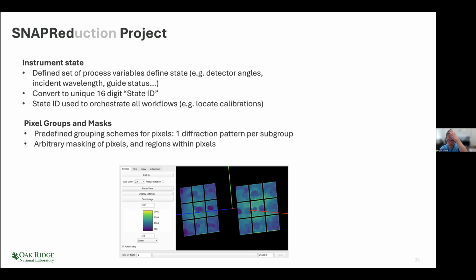And then finally, it also supports arbitrary masking of pixels and regions within pixels. And this shows a typical mask which has been applied to remove those diamond spots. And just to underscore, the binning and the histogram minimum and maximum limits are all recalculated on the fly to respect any masking which is done to remove pixels, because that would change the weighting of how the conversion from time of flight to d-spacing happens.